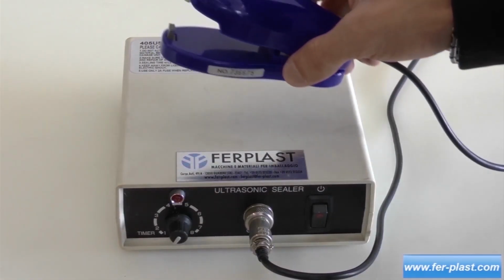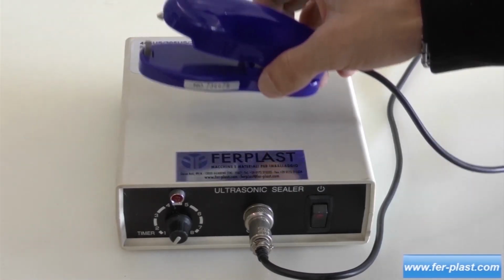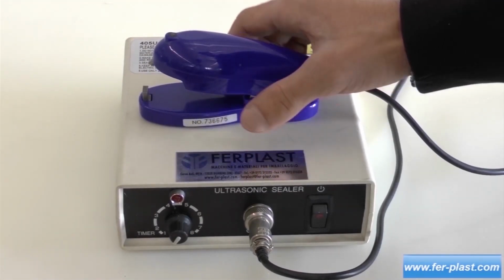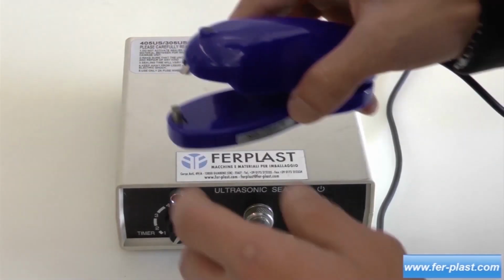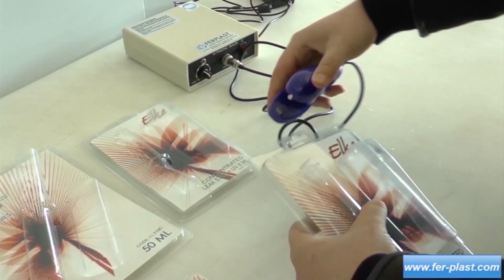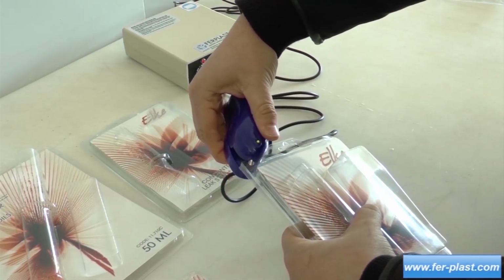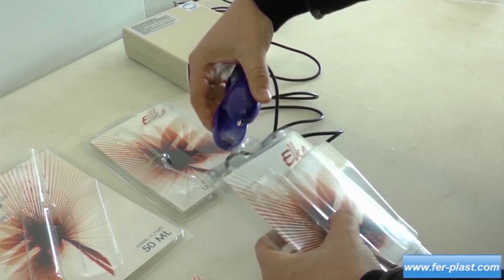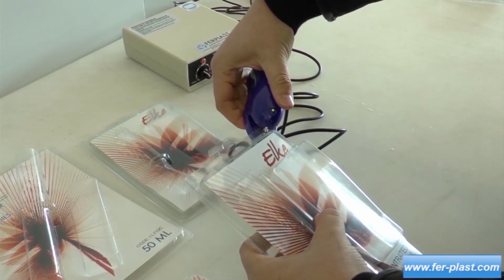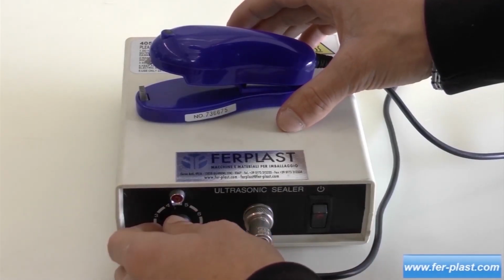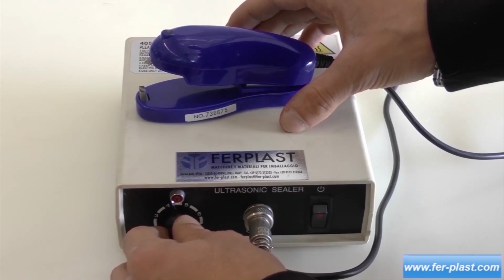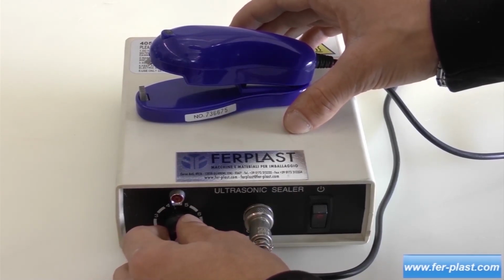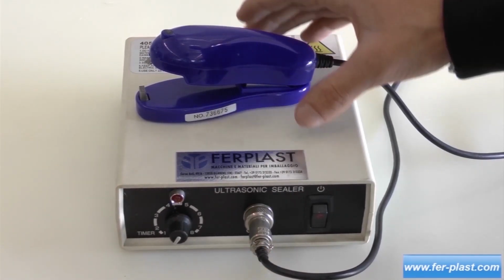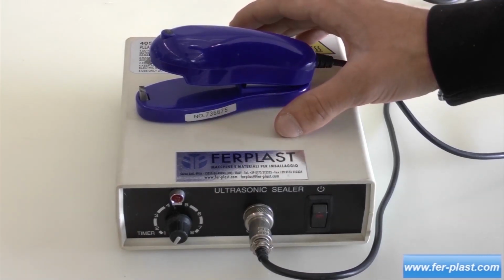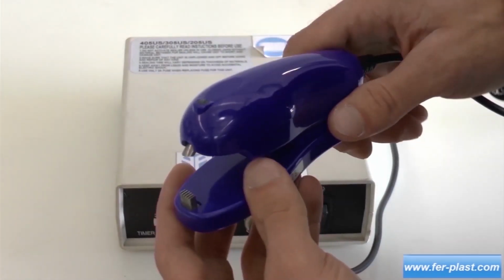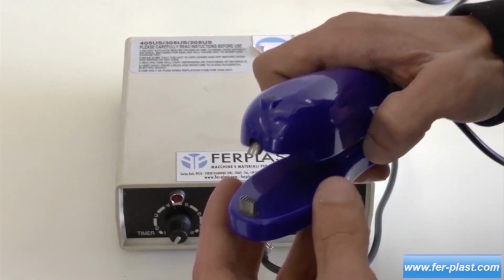The 405US is an ultrasonic clamp welding machine for sealing trays and blisters. The heat developed by the friction is transmitted to the two plastic surfaces and secures them instantly with a resistant point and without burrs. The welding power is adjustable by potentiometer and can produce an ultrasonic vibration of 55 or 60,000 cycles per second. The bar has a width of 3 mm and a length of 4 mm.